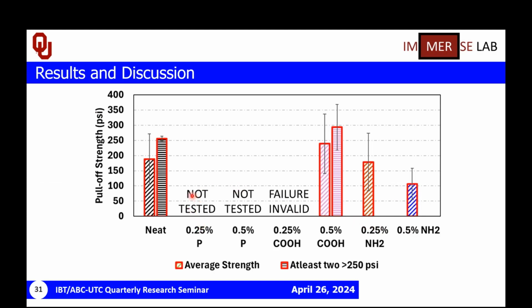As you can see, the neat polymer concrete showed a higher pull-off strength. 0.5% COOH showed higher pull-off strength in comparison to the neat polymer concrete and all of the others. And also for 0.25% and 0.5% NH2, we didn't have results where at least 2 of the specimens had a pull-off strength of more than 250 psi.